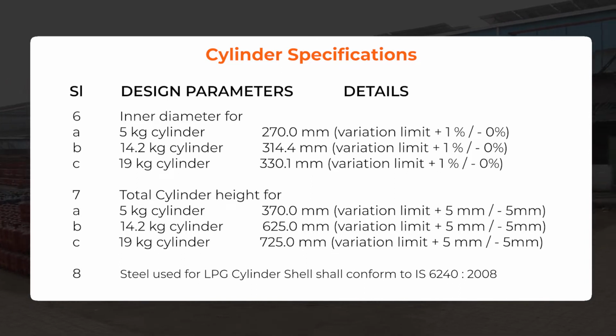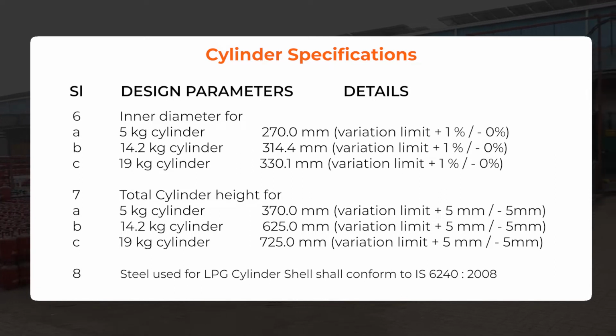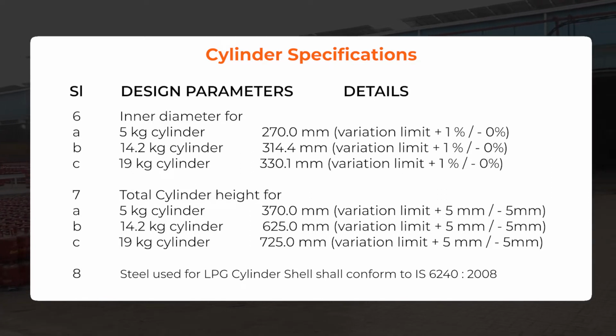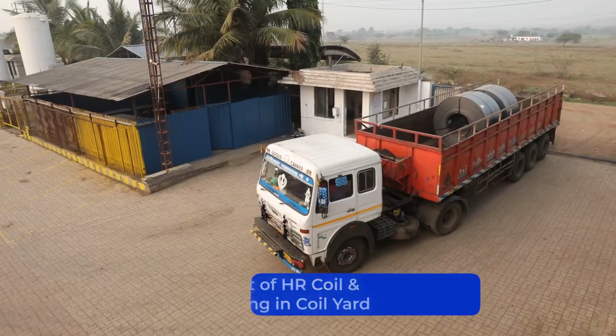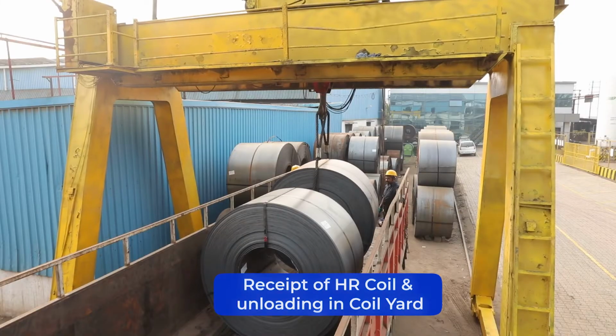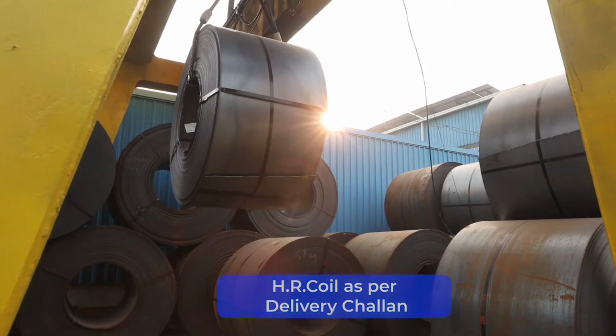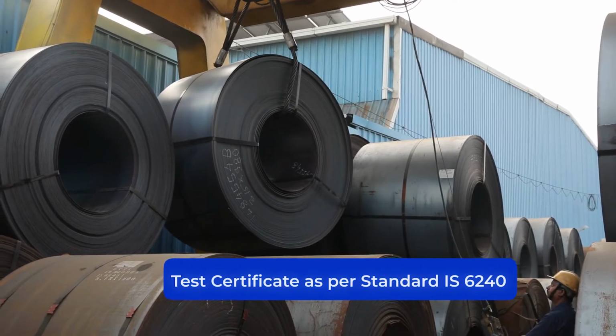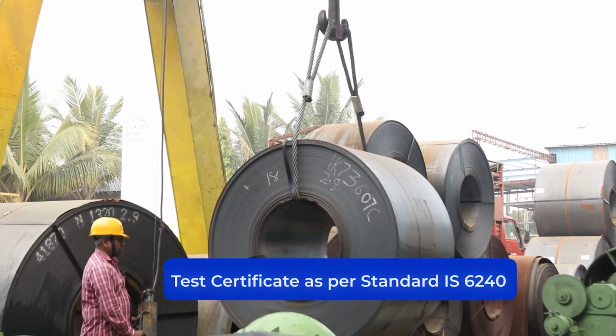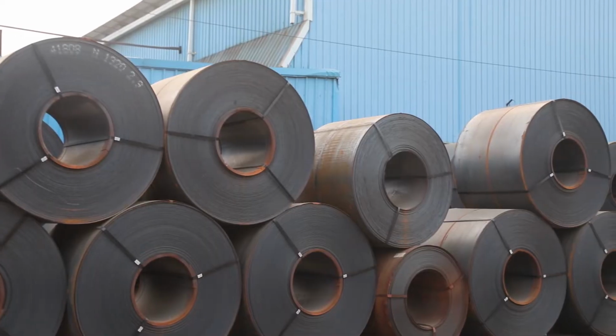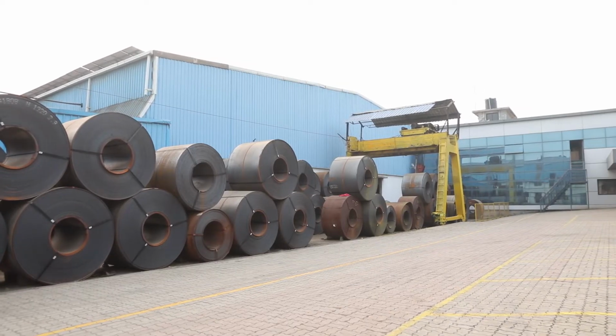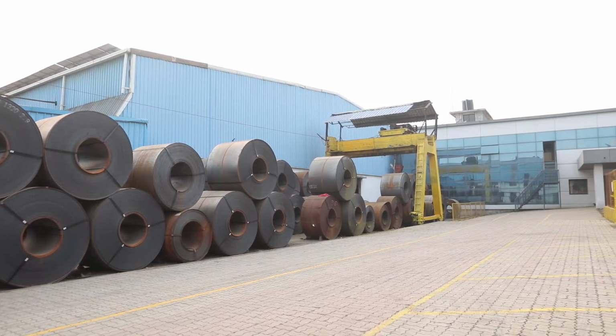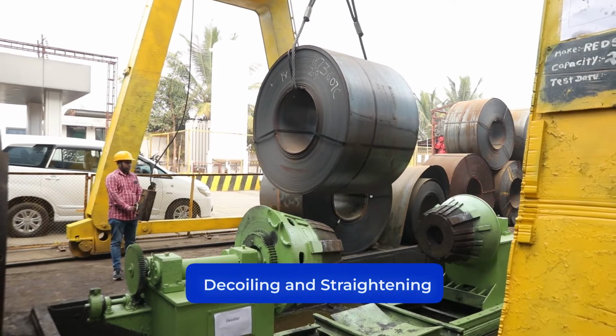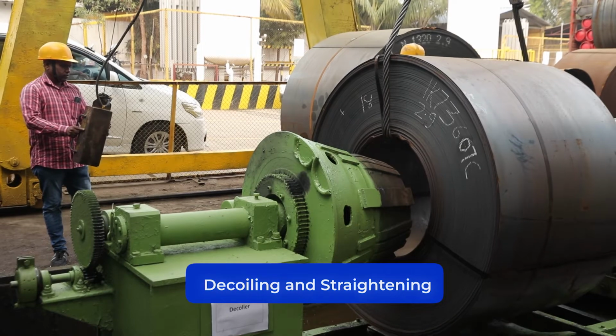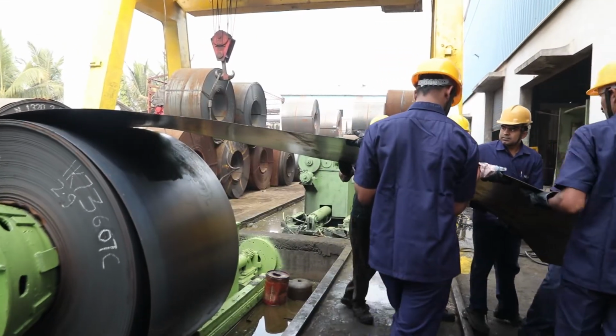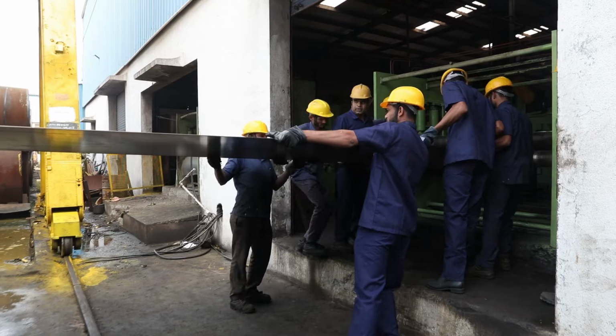Steel used for LPG cylinder shall conform to IS 6240 2008. It all starts with receiving the hot rolled coil as per delivery challan and test certificate as per standard IS 6240. Test certificate is used to verify the cast number and coil number. As we begin, put up HR coil on the decoiler for straightening. It's important to inspect the coil for thickness and width.